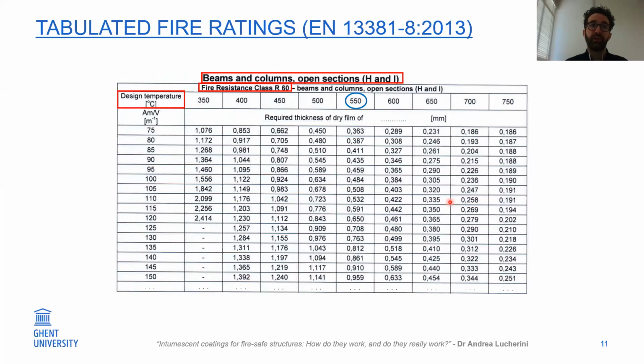Then the structural engineer, usually based on the utilization factor of your structural element, can decide the design temperature, or you can also take it with a sort of a priori approach. And then you define the section factor, which is the ratio between the exposed area of your steel section divided by the volume of the steel. And by crossing this information, you can get the minimum required dry film thickness of your coating. Dry film thickness means when the coating is dry, not when it's wet, in order to achieve this specific resistance class.